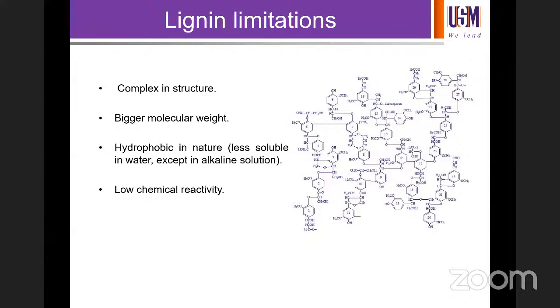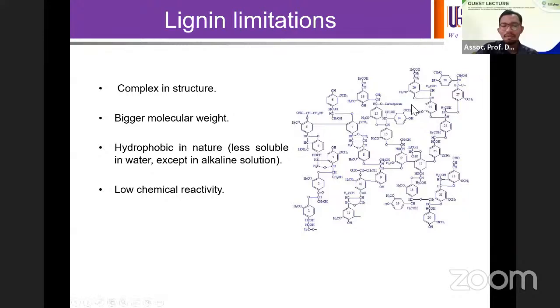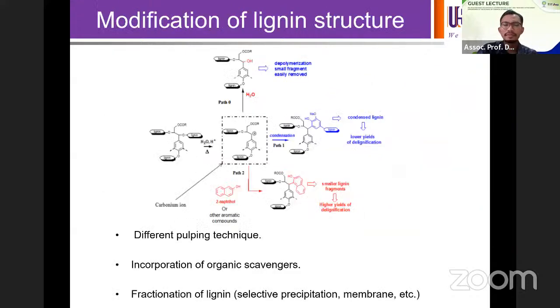We have a very low chemical reactivity. It means that with the structure of the lignin itself, if you want to do some grafting or some modification, it will be difficult, because the structure itself is quite stable and it doesn't have much active site for interaction. So all these are actually our limitations, which we have to tackle during our research.